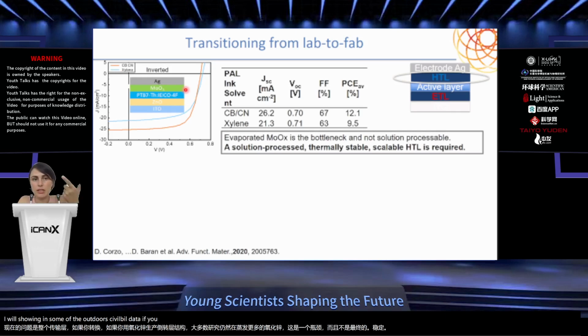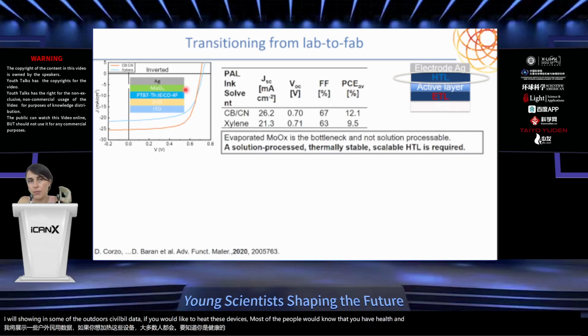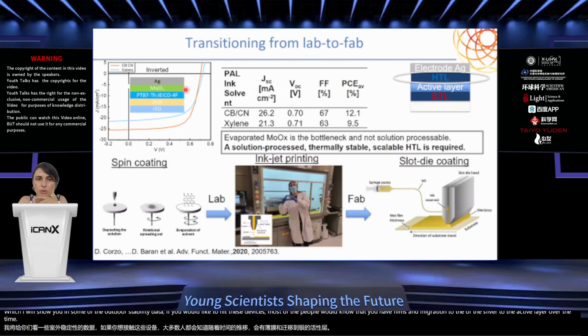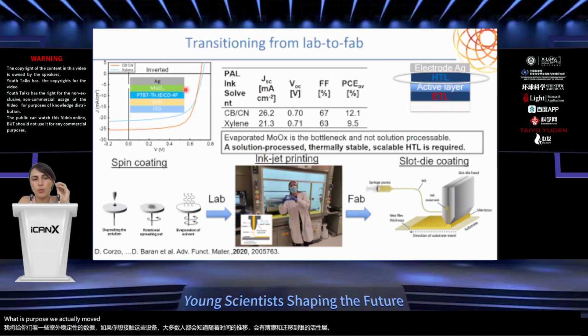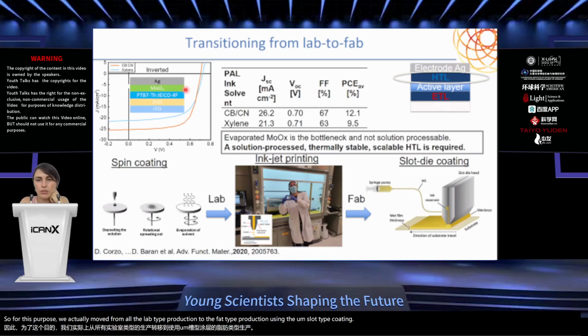If you would like to heat these devices, most of the people would know that you have shunts and migration of the silver to the active layer over time. So for this purpose, we actually moved from all the lab type production to the fab type production using slot die coating in order to look for solution processable hole transport layers.